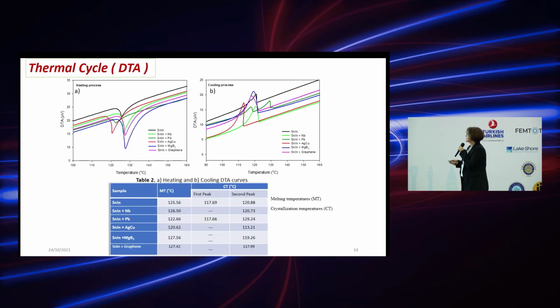Sorry. So let's have a look at the thermal cycle. In the thermal cycle, the low temperature is quite important, and we already know silver is quite efficient at reducing the melting point. Here we don't see a rise. Niobium is also a bit increased, and magnesium diboride and graphene show a similar honeycomb microstructure and a similar melting point.